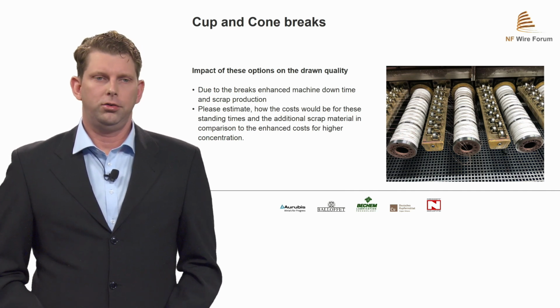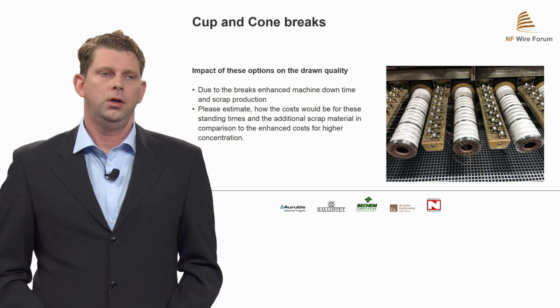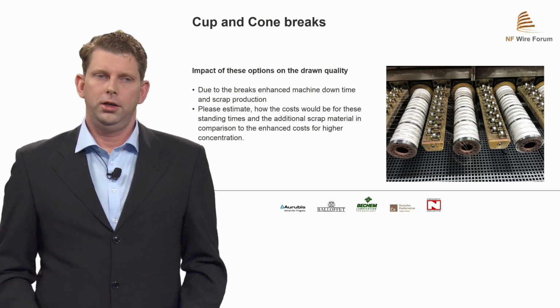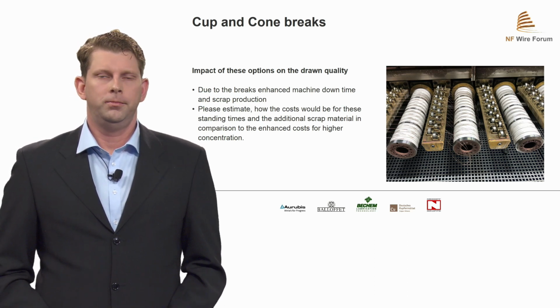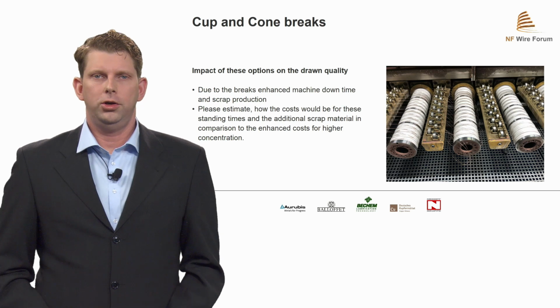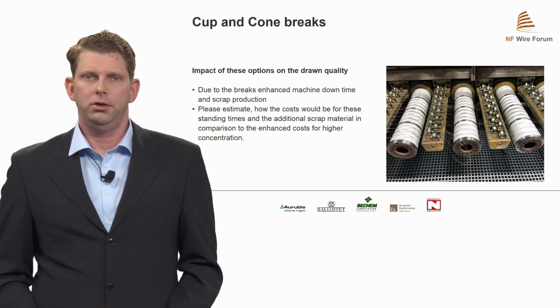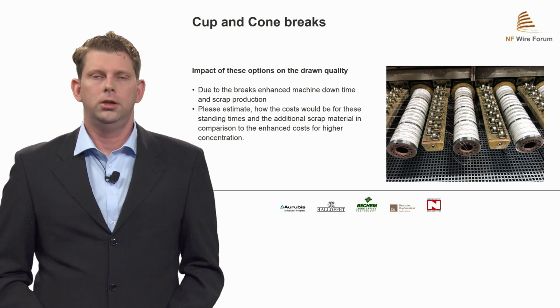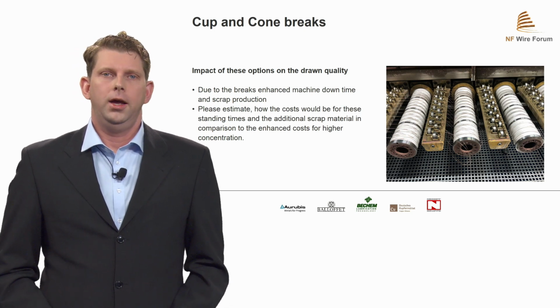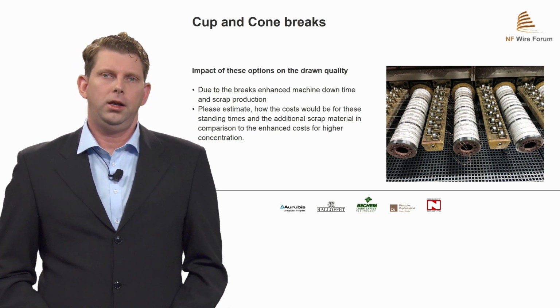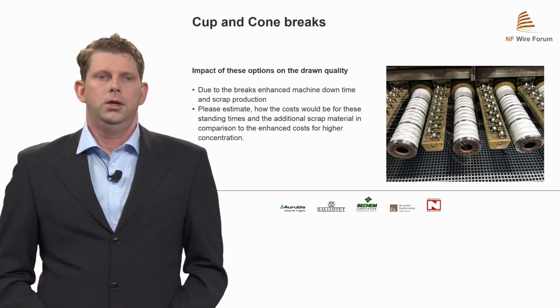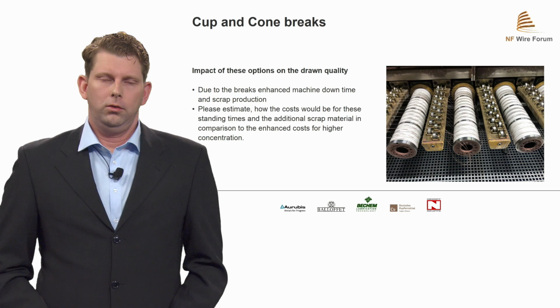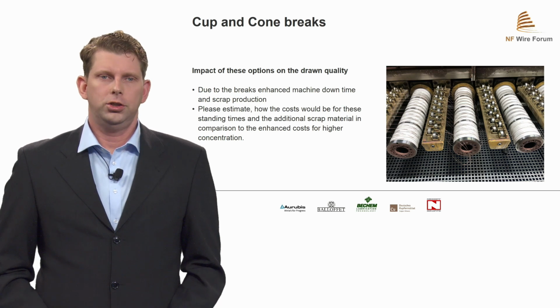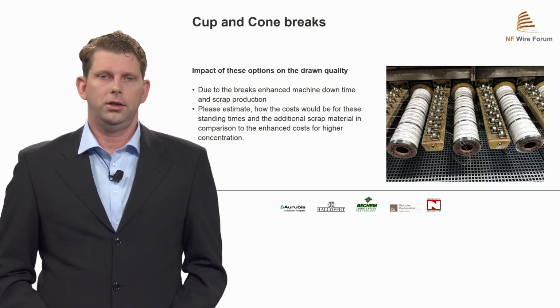Nevertheless, besides the driving concentration, you should also look on the other parameters of the emulsion. The emulsion is not only the concentration, it's also the pH value, which gives you an indicator for microbiological impact, for example, and all the other figures which can be analyzed by the lubricant producer, so for example by us. And we are always warmly welcoming you, if you have a question, to come to us and ask us.